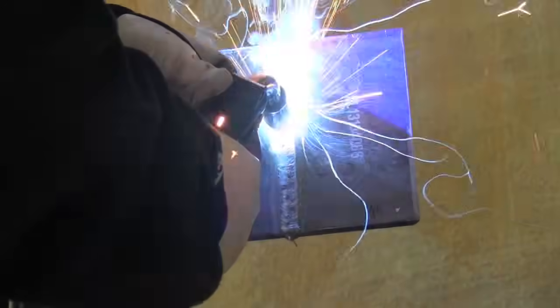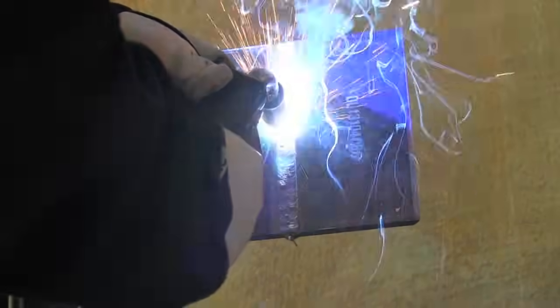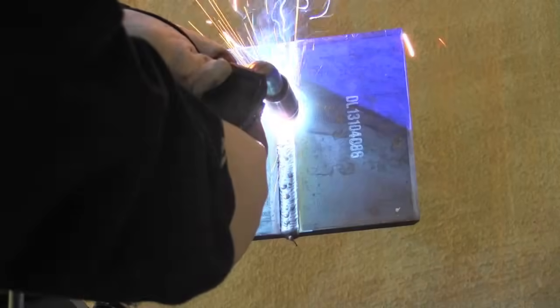Now you want to be flat across the face of this pass. And that means keeping a nice close stick out. And it also means coming out far enough on the bevels, but you don't want to chew them off. So stop maybe a sixteenth short of the bevel on each side.